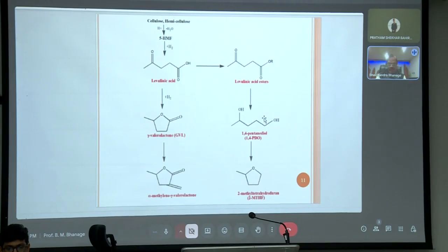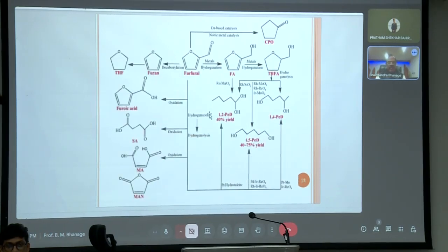Esters can be converted to 1,4-pentanediol, again a useful molecule for polymerization, or you can cyclize that to produce 2-methyltetrahydrofuran, again an important solvent, or levulinic acid can be cyclized to give you gamma-valerolactone, again a very important solvent. So many possibilities exist in the catalytic biorefinery. Then, as I told you, furfural can be converted to furan, THF, and then we can perform so many operations to get many other products like furanic acid, succinic acid, malic acid, maleic anhydride, FA, then you can do the hydrogenation, you can get THFA, CPO, then you can get the 1,4-pentanediol, 1,2-pentanediol, based on the various catalytic processes.